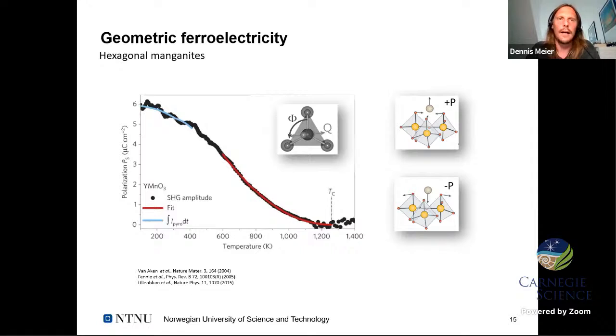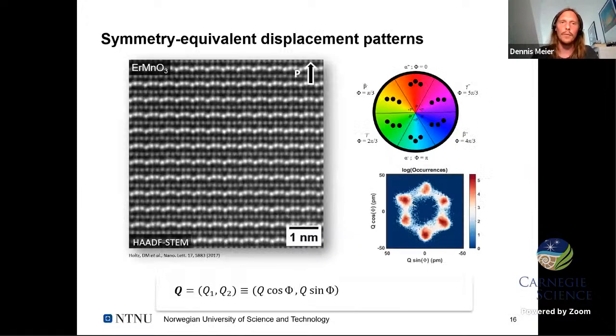Let's also look at the other type of improper ferroelectrics, hexagonal manganites with geometric ferroelectricity. Here, yttrium manganite is one of the model systems. What's happening here is at about 1250 Kelvin, the system goes through a structural phase transition, and along with the symmetry reduction, a ferroelectric polarization shows up. What's happening is that these manganese oxygen bipyramids buckle and tilt, and they push the rare earth atom up, or if they tilt in the other direction, it falls down, and we get characteristic displacements that lead to the polarization.